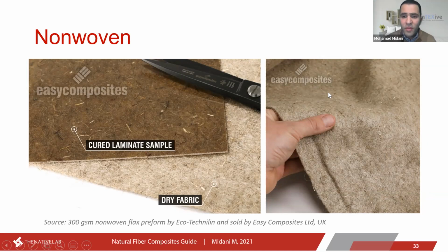Also, the most commonly used natural fiber preforms are, as I said, non-woven. And in this case, it's a non-woven that is blended with polypropylene fiber. So it's 50% natural fiber and 50% polypropylene fiber. And this is the standard used in the automotive industry, where the mat is considered like a dry prepreg, and it's taken directly to the compression molding, and it's just compression molded, and the composite is ready to use.